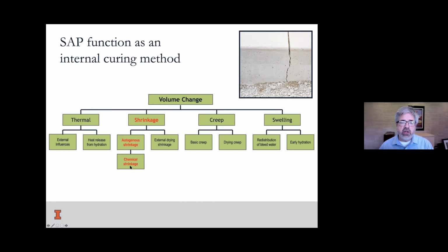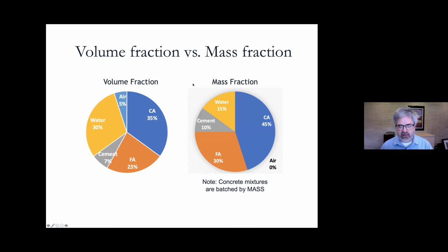The shrinkage, you can't avoid this. This is part of hydration. That, and I'll see it on the next slide, that we encounter this chemical shrinkage, and it drives a certain kind of a desiccation of the internal microstructure unless we do some things about it. And of course, the whole idea of avoiding volume change is, let's see if we can get rid of the cracks. We'd like them not to be there.